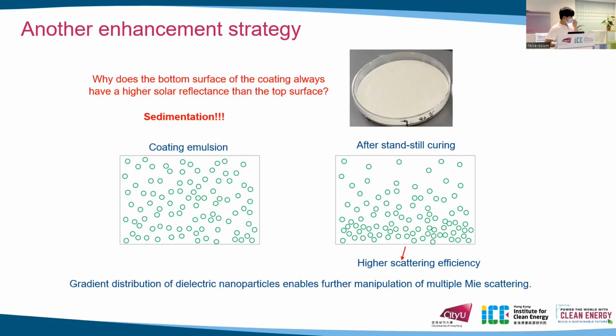After considering its production process, we think that sedimentation may have occurred in the curing process, because we prepare the coating first by mixing the polymer emulsion with functional fillers. At that time, the fillers are randomly dispersed in the coating emulsion. However, after curing, the fillers may settle down, and the bottom surface has a higher density of fillers and then has a higher scattering efficiency. So this gradient distribution of fillers caused by sedimentation may provide another strategy to further manipulate the multiple Mie scattering for the TiO2-based coatings.